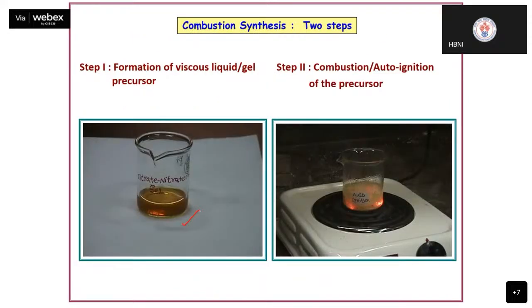This is how my solution looks, and I evaporate it, get a gel, and this is called auto ignition. This is how it looks when it burns in the beaker. Of course, whether it gets burned in the beaker also depends upon the oxidant to fuel ratio that you have to tailor. If the oxidant to fuel ratio is stoichiometric, you will get such kind of flames. I normally work in fuel deficient condition, because fuel deficient condition helps you to not achieve very high temperature. If you are not going to very high temperature, then your particle size will be smaller.